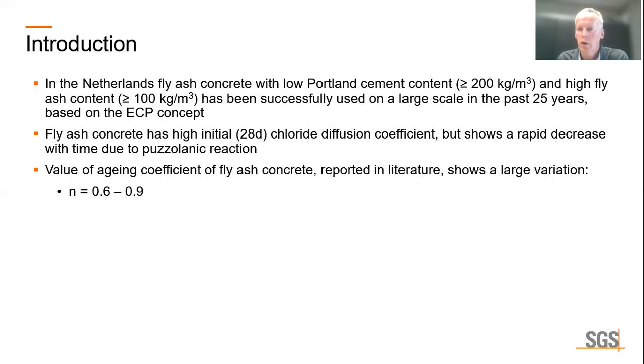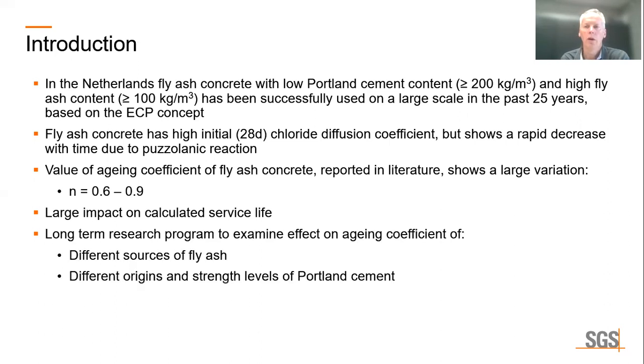Values of the aging coefficient reported in literature show a very large variation between 0.6 and 0.9, and such a variation has a very large impact on calculated service life. Therefore, a long-term research program has been performed to examine the effect on the aging coefficient of different sources of fly ash and different origins and strength levels of Portland cement.